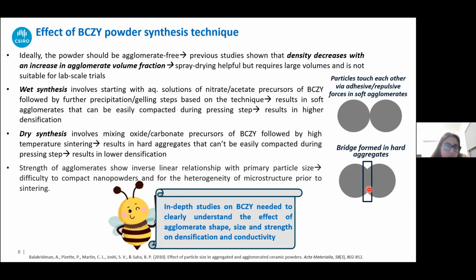So more in-depth studies are needed to find out how the shape and size of the agglomerates affect the sintering technique, whether co-pressing, co-sintering, or even if you are not planning to press and are going for another electrolyte technique like tape casting, dip coating or spray coating. There also these agglomerates can have an effect, and more in-depth studies are needed for that.